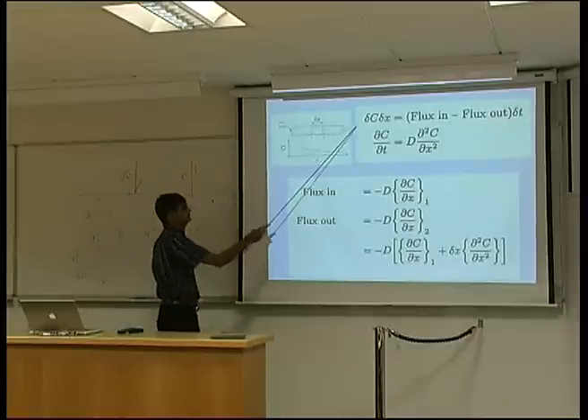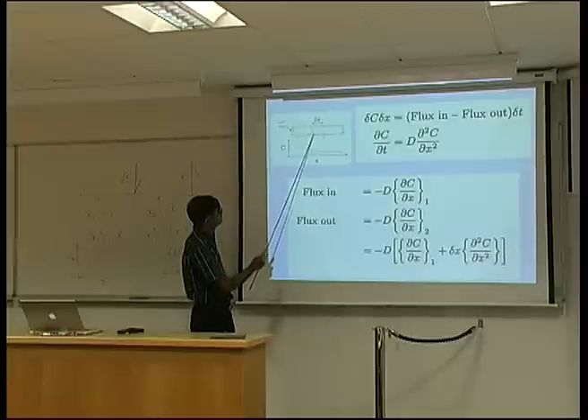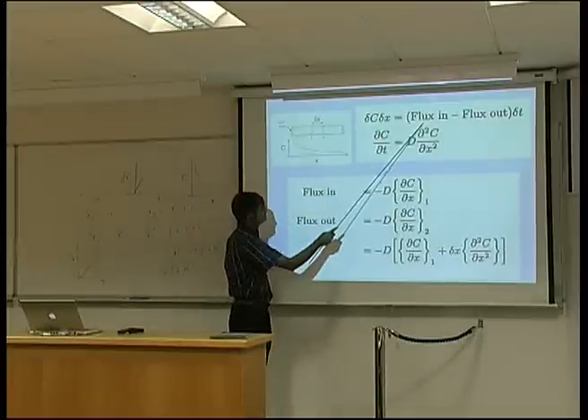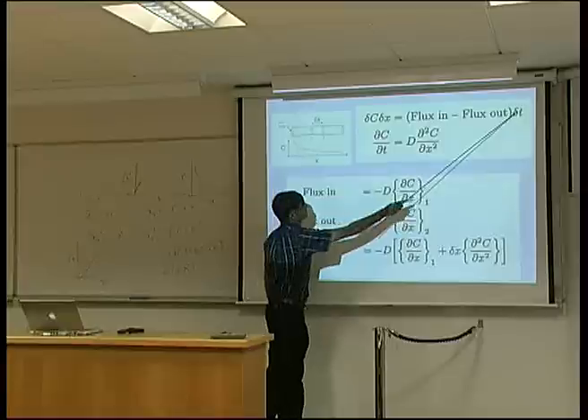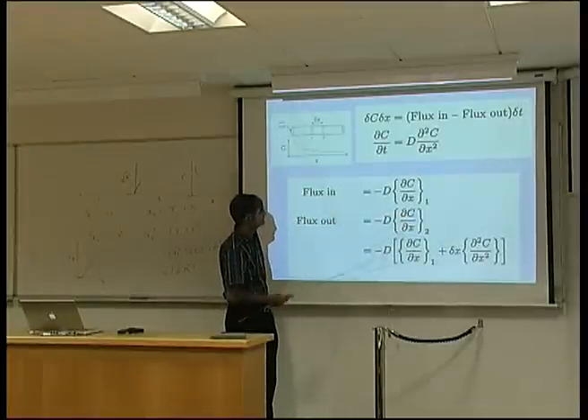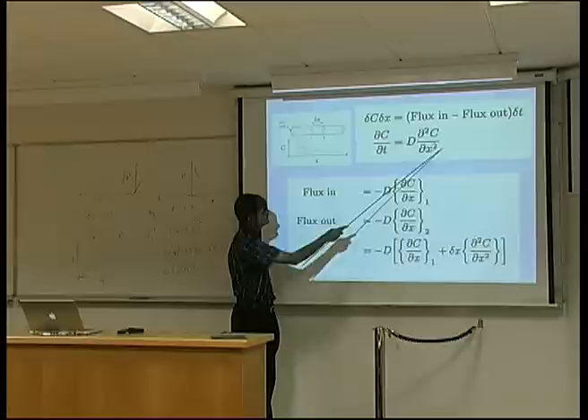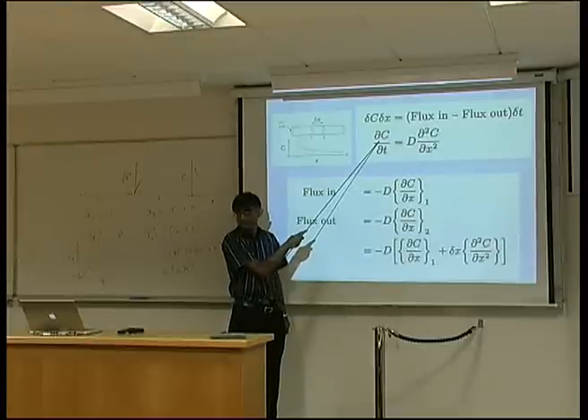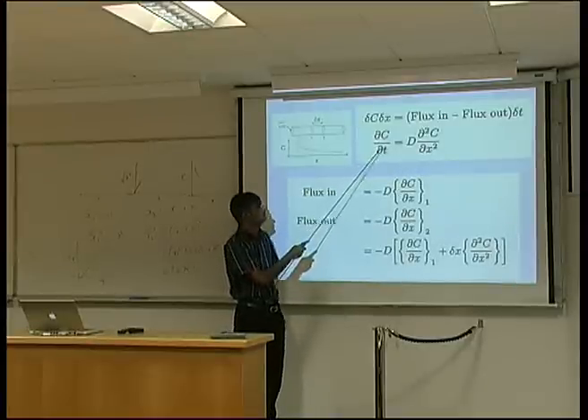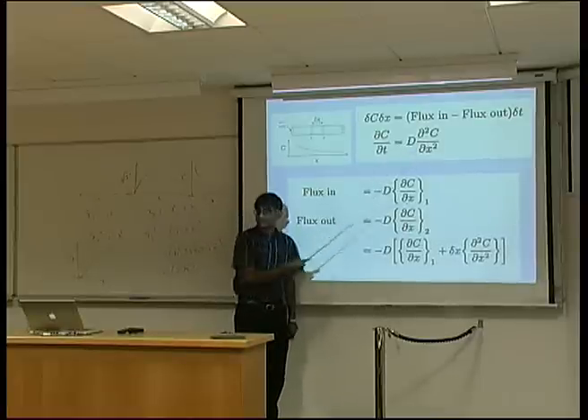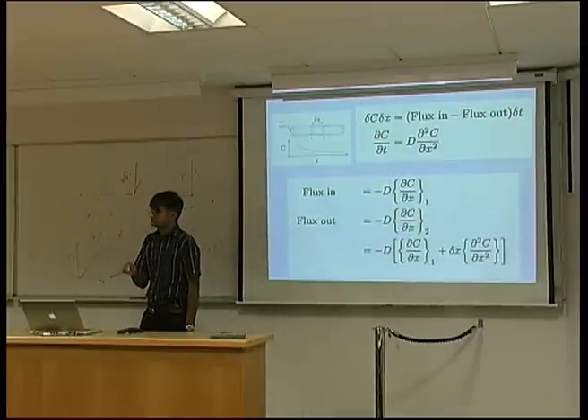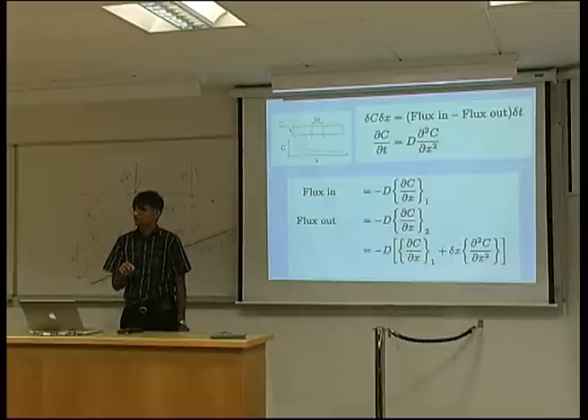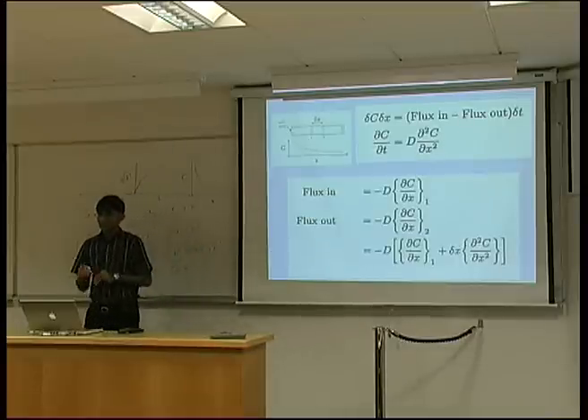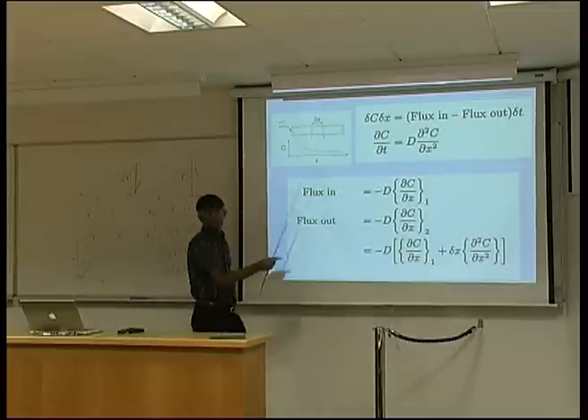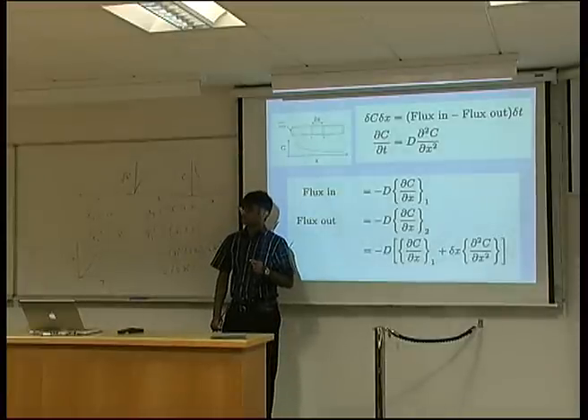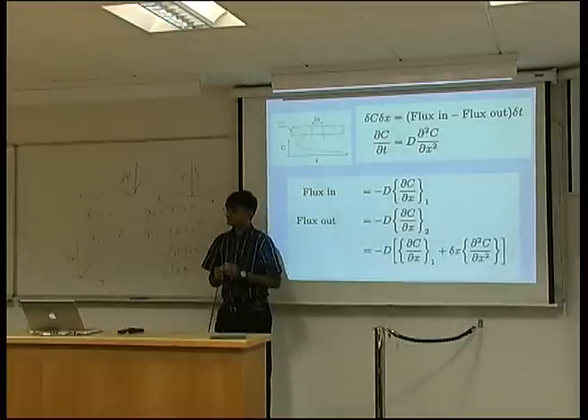So we have dc times dx, which is this volume of material, equals the flux in minus flux out times delta t. Okay, so we just substitute these terms in here and you find Fick's second law: the rate at which concentration changes with time is equal to D times the rate at which the gradient changes with distance. If this is zero, then the concentration doesn't change with time, and we end up with Fick's first law.